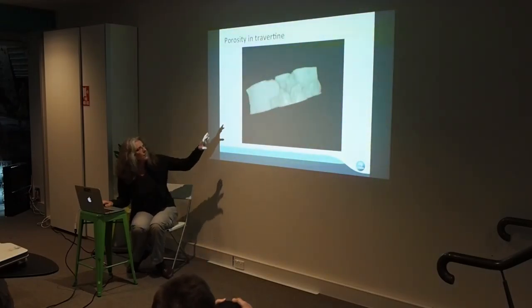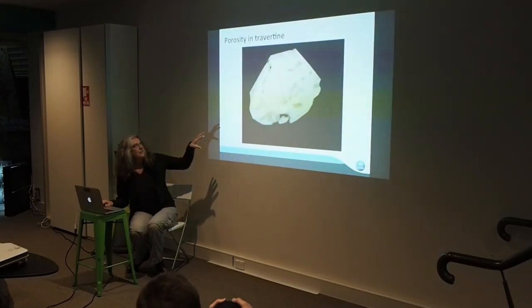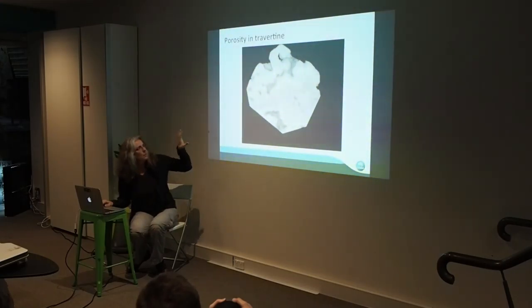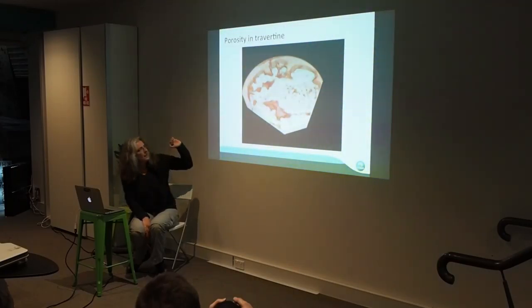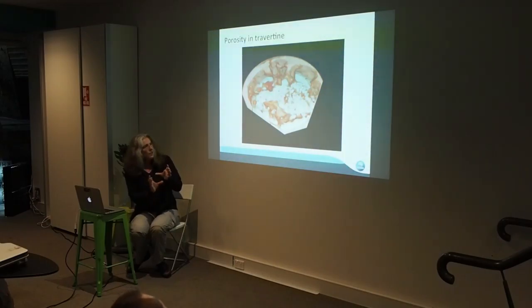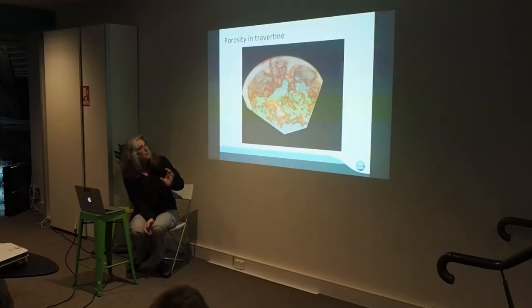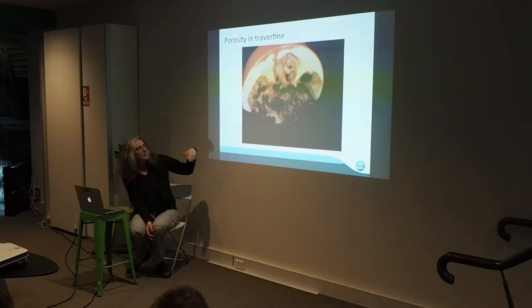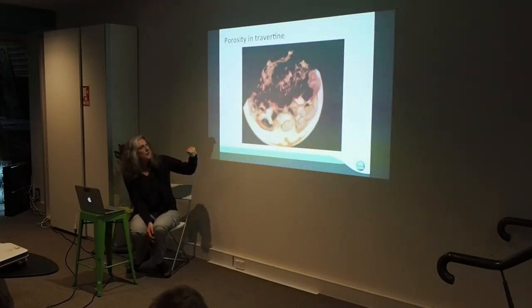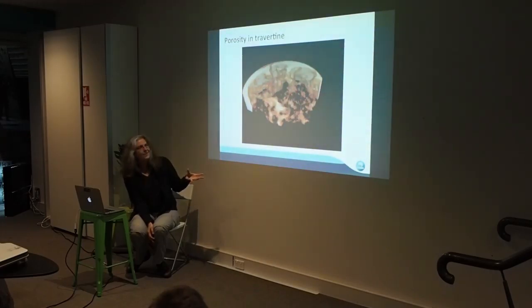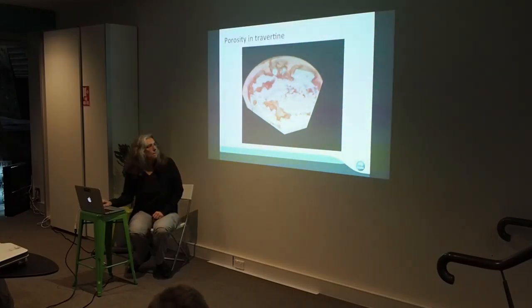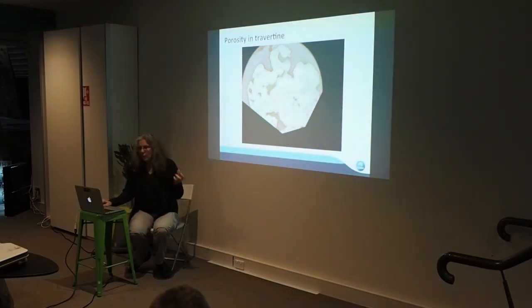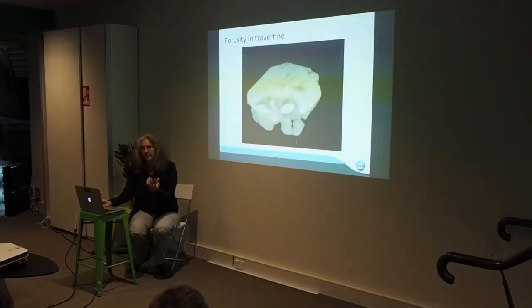This is travertine marble, and we put Xenon into it to see where the pores are. The Xenon shows in red. In this rendering, because what they're interested in is where the pores are, I've used the two images — the Xenon image and the sample image together — and made the sample image fade away so you're just seeing where the Xenon gas went. This shows us the pore structure, which is actually what they're interested in. In that particular sample you can see quite a lot of the pores just from the image because they're big enough to resolve.